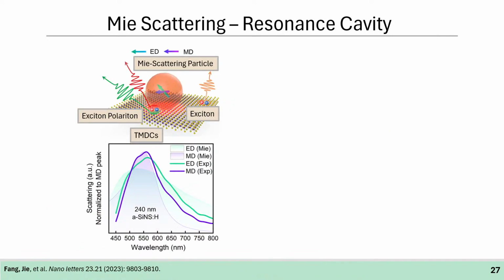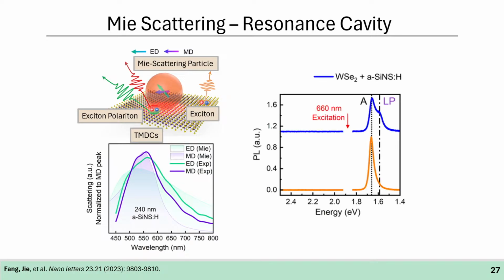Another application for Mie scattering, and that is of interest to me, is that we can couple transition metal dichalcogenides, the materials that I was talking about in the beginning, with particles that have Mie scattering. The transition metal dichalcogenides support excitons at room temperature, and the particle can supply a resonance cavity, and that way we can confine exciton polaritons, which can be used for exciton polariton lasers, for example. When we have our Mie-resonant particle, by simply measuring the photoluminescence, we can identify the excitonic position and the lower polaritonic state. And when we don't have the particle, we obtain standard photoluminescence emission.